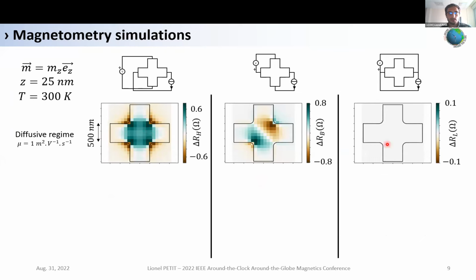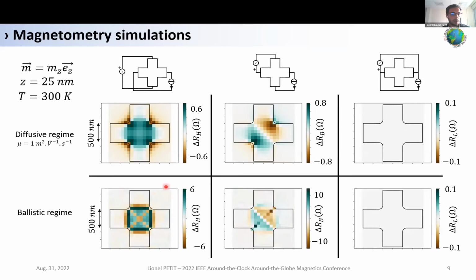And these different maps correspond to different wiring configurations. Here you have the typical Hall configuration. Here you have the bend configuration. And here the longitudinal one. You can see that in longitudinal configuration, we do not have any signal. And it is because of the parity of longitudinal resistance versus B. But if we switch to ballistic regime, we win one order of magnitude in terms of signal amplitude, which is really cool. But everything will depend strongly on the position of the dipole.